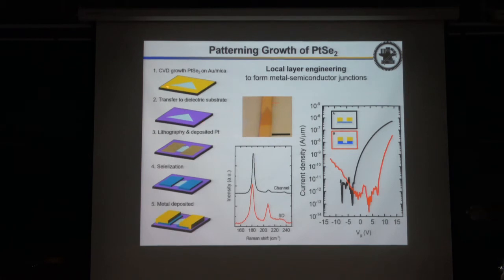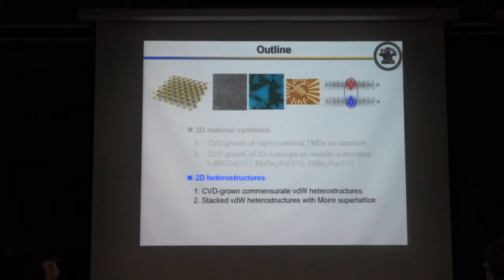For example, we have a semiconductor here, one monolayer, and then we use lithography to try to increase the thickness. How to do that? We just deposit platinum at the contact area, followed by selenization. The temperature is not high, maybe just 300 or 400 degrees C in a selenium environment, and it will convert platinum into platinum diselenide, and then we deposit metal. So you can use this way to improve the contact resistance. This can also be applied to electronic devices.